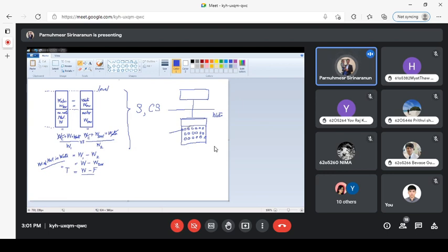Sometimes the holes of the basket are not small enough. So almost always in the lab, the basket is used for crushed stone and the bigger one for sand. ASTM uses the bigger one to measure the specific gravity of sand and the measuring device with the basket to find the specific gravity of stone in water.